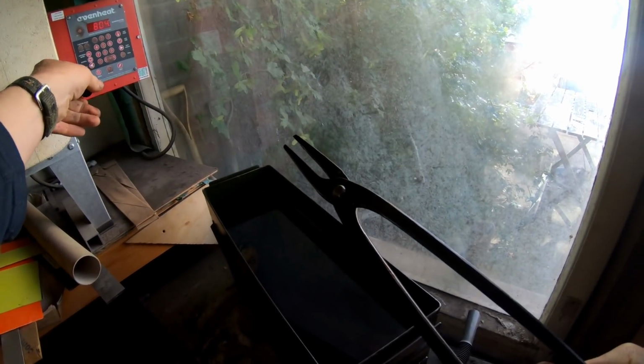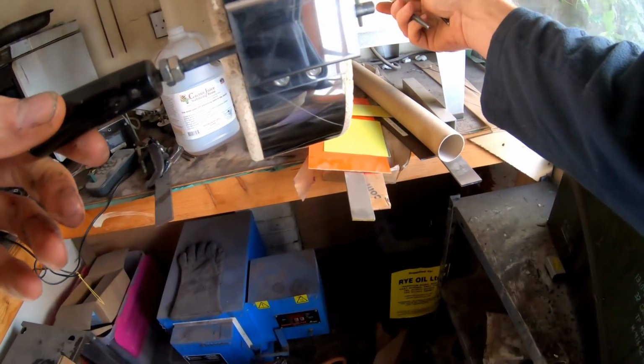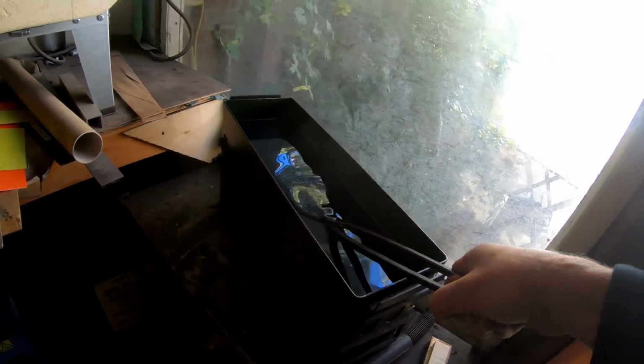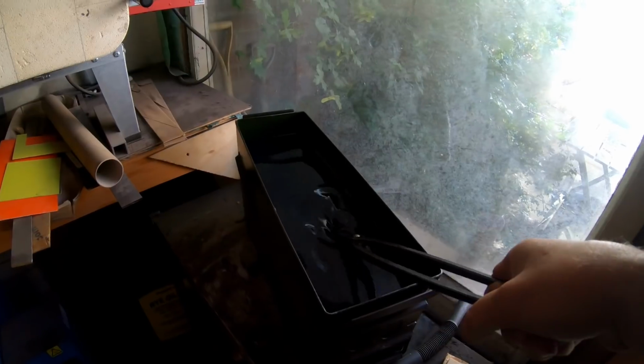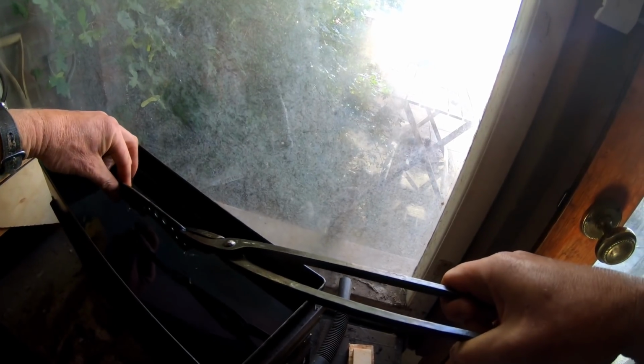The key to a good heat treat is getting your blades quenched down really quickly. So there's no hesitation, straight into the oil. A nice slicing motion. That's the blade submerged at the moment, and then goes the handle. And that blade should be unholdable in next to no time. Now that'd be fully hard.